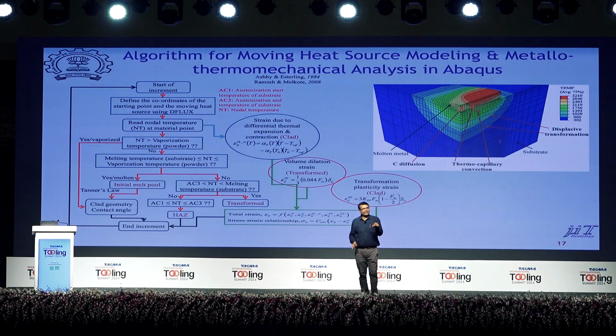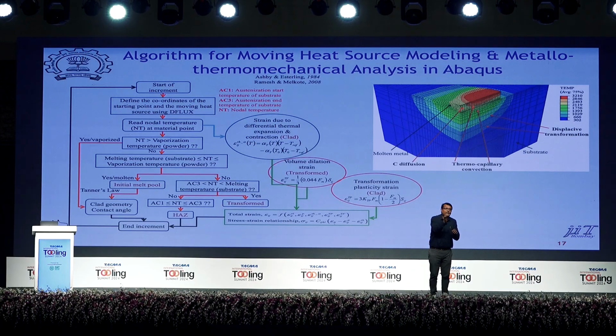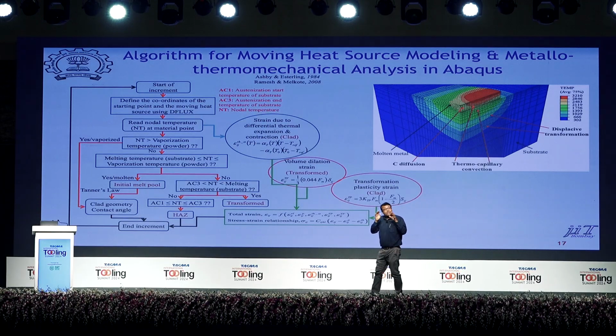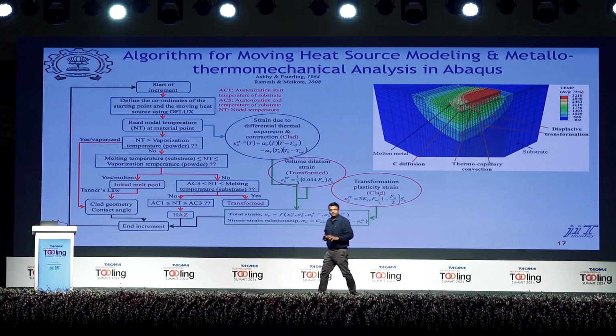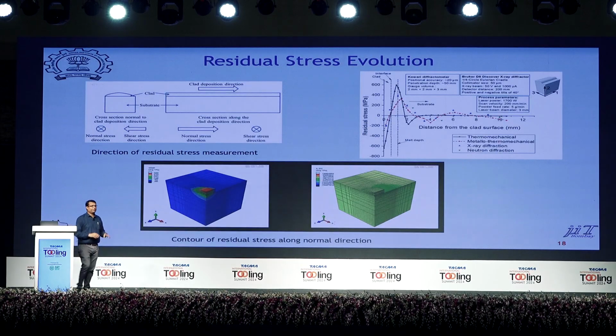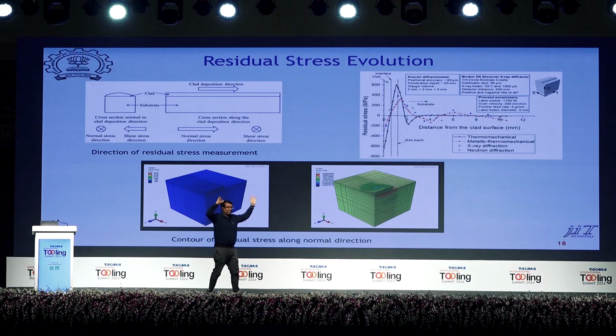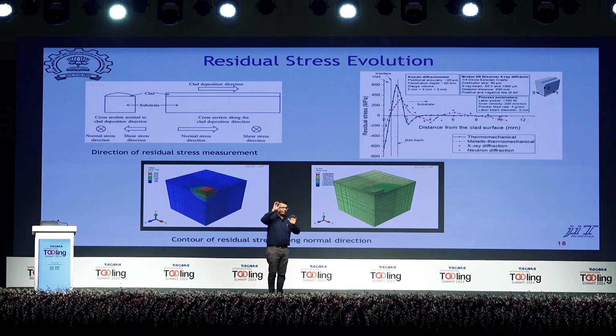And if you don't account for that, we're not able to know what kind of residual stress will be there. And if your residual stress is tensile, in that case, if there is a small crack, it will propagate. So if you understand that fully, you will have a much better quality of deposition. So that's the moral of the story here. So we developed this model, we did the testing. We used neutron diffraction, which is a really fancy thing, measured the residual stresses, bulk residual stresses, and then finally calibrated the model.